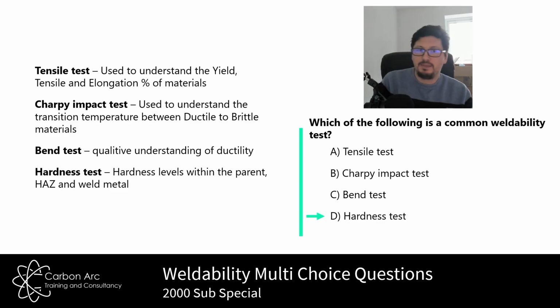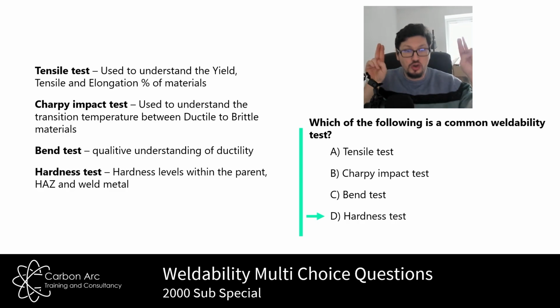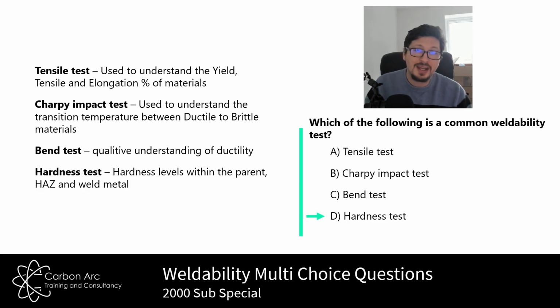And we can test in the base material, the heat affected zone, and the weld metal. Our different standards give us different amounts of levels for this. If you look, say, in ISO 15614, it's saying a hardness value of 380 for normal materials, so normal carbon steels. Can't go above 380, because above 400 we're likely to have martensitic structures. So we can hardness test something, and if the parent material is really hard, the probability of weldability being poor is increased.